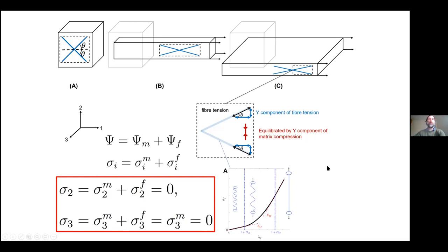So what's happening here? Well, basically, the fibers are very nonlinear. Usually when a fiber is not under stress, it's got this wavy configuration. If we look at SEM images of the fiber network, we can often see waviness in the fibers. And then as we stretch them, we start to straighten out the waves. But when we straighten out these undulations, these waves, the material becomes stiffer. We can see this nonlinear increase in the stiffness. And eventually it becomes fully straight, and we say then that it reaches this large deformation stiffness.